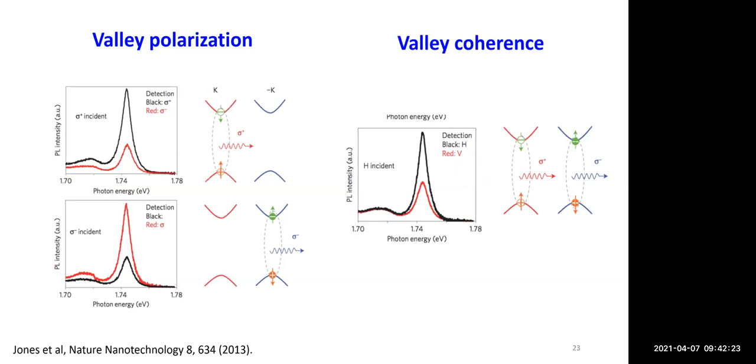In most of these experiments in the bare monolayers on a substrate, the optical pumping of the valley polarization and the optical generation and manipulation of your valley coherence have all been observed at cryogenic temperatures, mostly liquid helium temperatures. But the major obstacle to coherently controlling this valley degree of freedom at room temperature is the intervalley dephasing processes, which can be mediated by phonons, and also by long-range electron hole interactions.